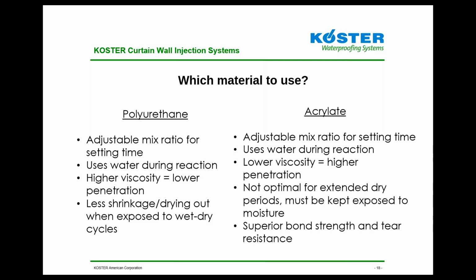Especially the acrylate products, the G4 and the S4, if they encounter water behind the wall as they're reacting, can use water outside of that 1-to-1 ratio potentially, and can swell with exposure to water after curing. So after it's cured, if it's exposed to water on the backside, it can swell and expand, giving an even better waterproofing barrier, even after the product is finished curing.